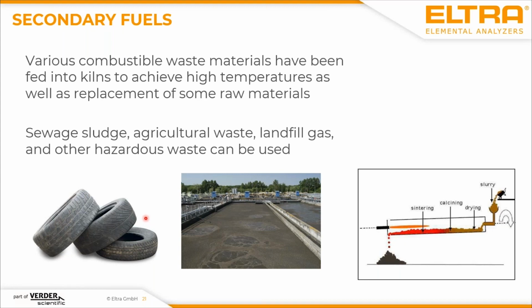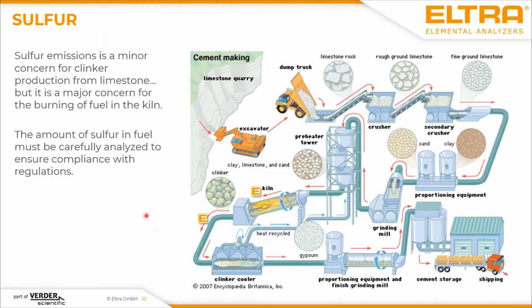Not only the carbon is important here, but also very important is the sulfur content. Why? For emission. The sulfur emission is a minor concern during the clinker production. There also we have a little bit, but it's not that much. But it's a big topic when it comes to the energy, because we have a high amount of emission there, or potentially high amount of emission. By controlling sulfur content in fuels, this can be limited.